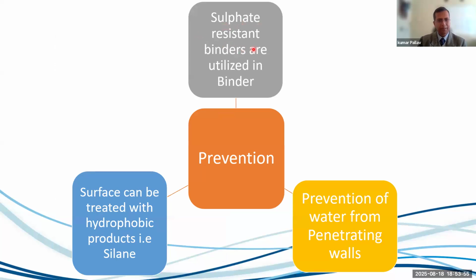Sulfate resistant binders should be utilized in the binder, so you need to see whether you have used those binders. Prevention of water from penetrating the wall is also something you need to look for. The surface can be treated with a hydrophobic product like silane, right? You should treat your surfaces with silane so that moisture cannot penetrate into the mortars.